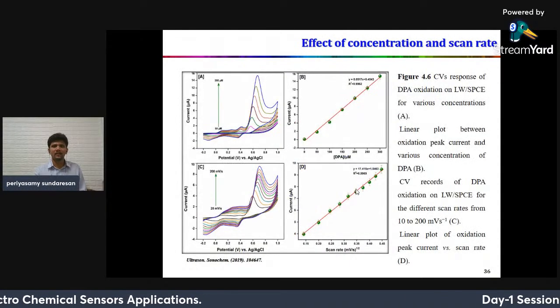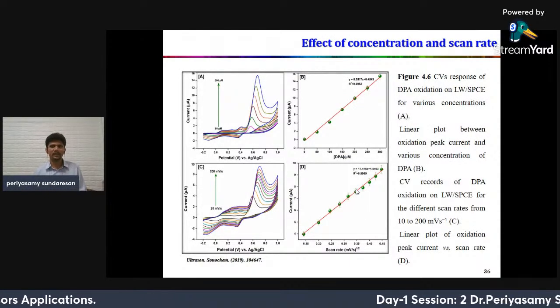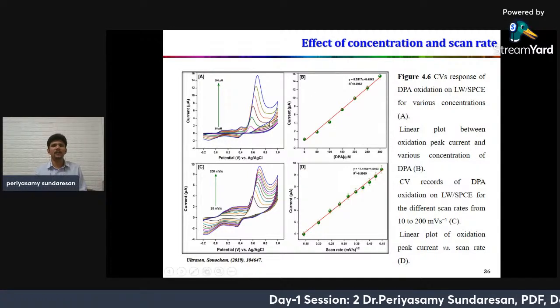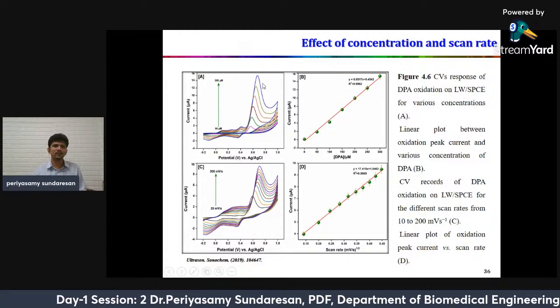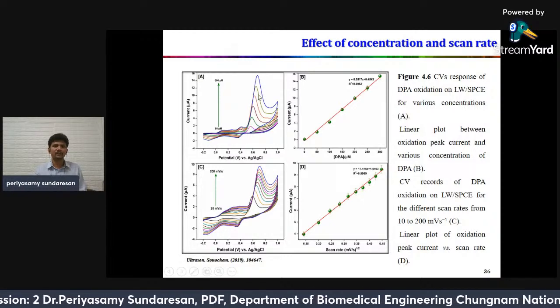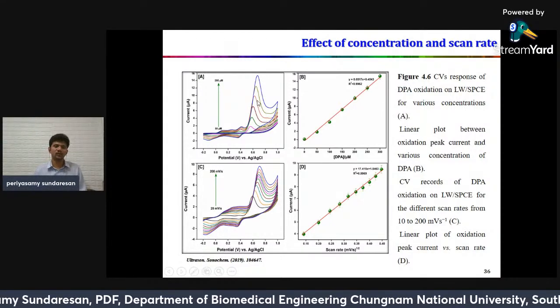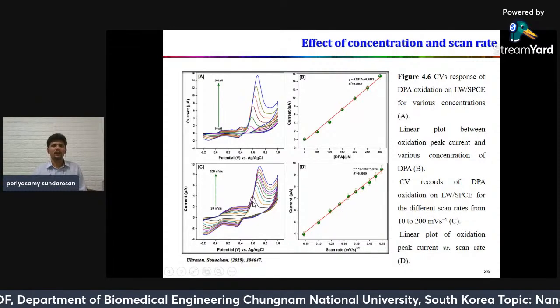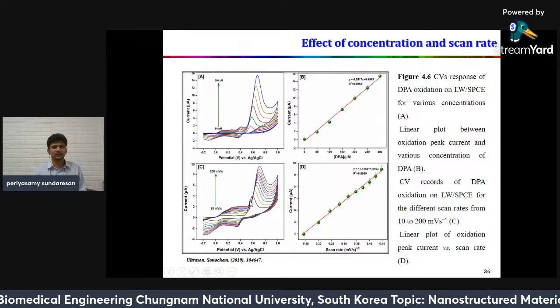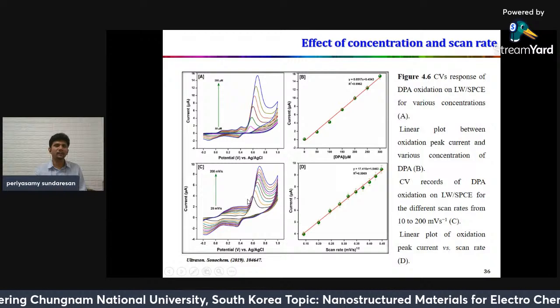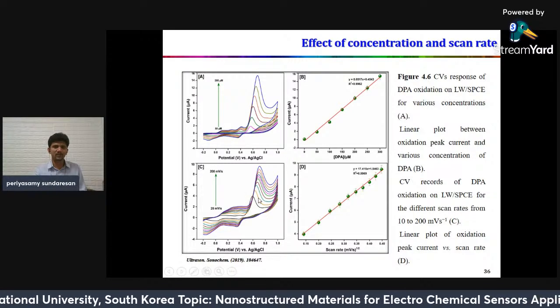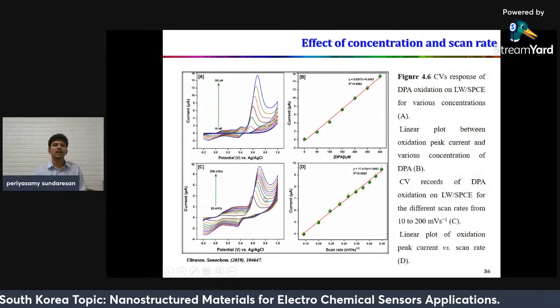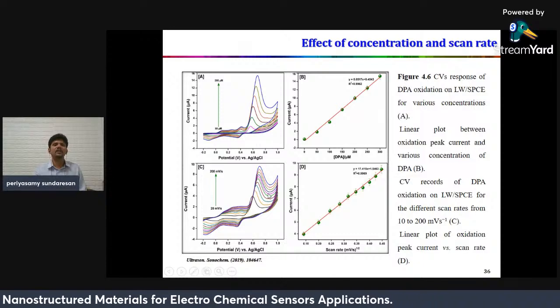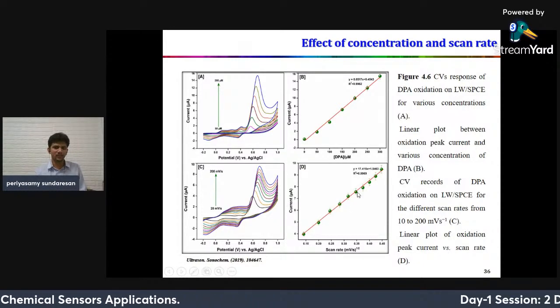Effect of concentration and scan rate studies. Here I have checked various concentrations, like 50 to 300 micromolar. If the concentration increases, the current intensity also increases linearly. In the scan rate study, the current increases linearly as the scan rate increases, but the peak potential is slightly shifted to the positive side. Under these conditions, this is not an adsorption controlled process. This is a diffusion controlled process.